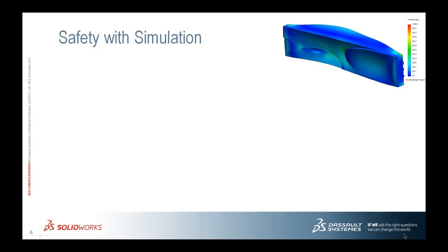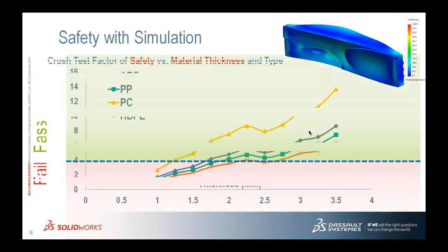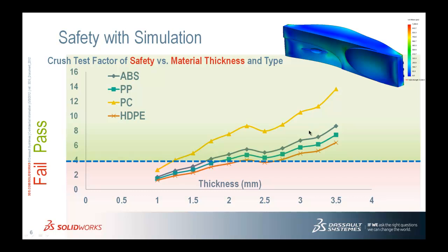So we've returned now to the PowerPoint presentation. Let's take a look at exactly what those runs have actually yielded for us. And what we can see is that for any of these materials, there is a thickness that will allow us to reach our factor of safety goal. For polycarbonate, that thickness is going to be 1.25 millimeters, while for an HDPE, a high-density polyethylene, it's going to be 2.75 millimeters. And various thicknesses for the other materials.